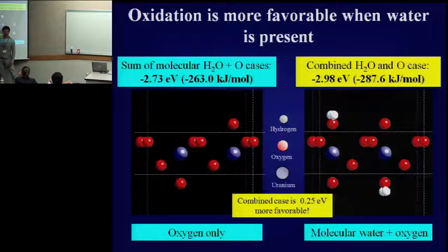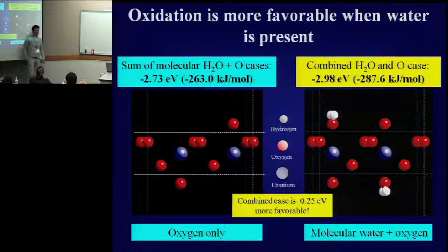And so what's the atomic picture of this? If you were trying to oxidize something like UO2 with just dry oxygen, if it was really, really dry in Nevada, it would take more than 1,000 years to oxidize even one monolayer. Why? It's the same mechanism that I was trying to explain to you before. This is diamagnetic, the oxygen in the air is paramagnetic. It does not want to transition unless it gets some help.